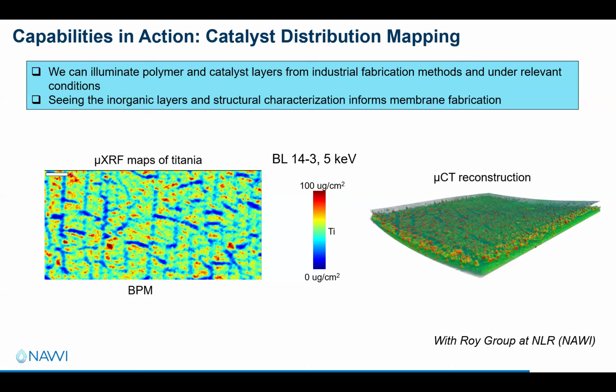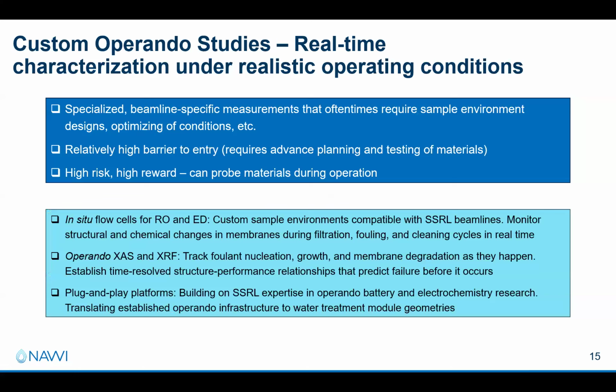There's also micro CT reconstruction. So there you can also look at what this membrane material actually looks like in 3D. How well distributed is my catalyst layer. And then as another thing, there are very custom setups. So those are the types of setups that really take advanced planning and then likely a couple of iterations. So that's where we can start looking at real-time characterization under realistic operating conditions. These are very specialized. They oftentimes require sample environment designs, and there's a relatively high barrier to entry. But it's a high risk, high reward situation.